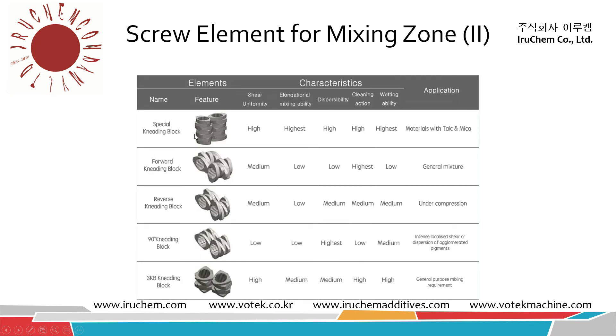This kind of element is also used for PP-talc or powder-heavy materials, because the powder that is not well mixed can go through the groove backward and has more chance to mix with the polymers later. There are also continuous mixing elements — when the material goes inside, the rotating screw element shape gives more possibility to mix together. This special kneading block is very effective for mixing powdery materials like talc and mica. The forward kneading block is good for general mixing, but its effectiveness is quite limited without a reverse conveying element or reverse kneading block alongside it.